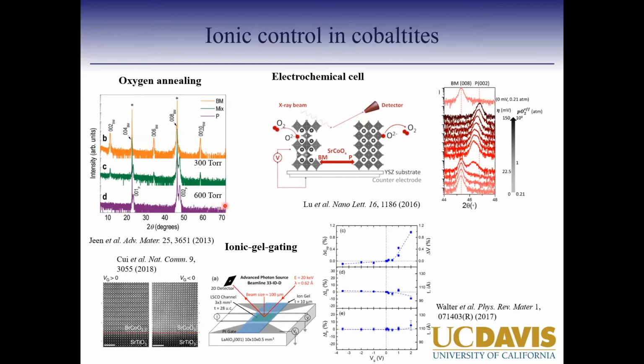Now, that's not a method you can use for device applications. So people have fabricated electrochemical cells or ionic gel gating cells where they apply a voltage and the oxygen ion moves in and out of the structure. And as the oxygen ion moves, people have tracked the transformation from brownmillerite to the perovskite phase as well.